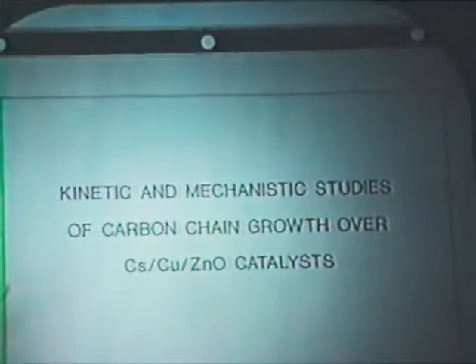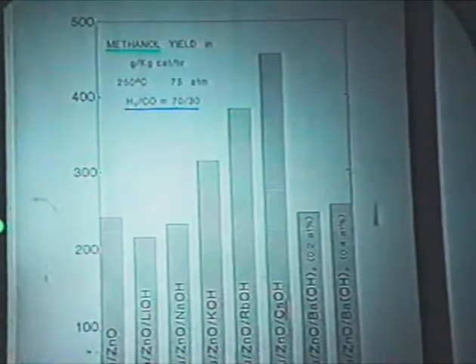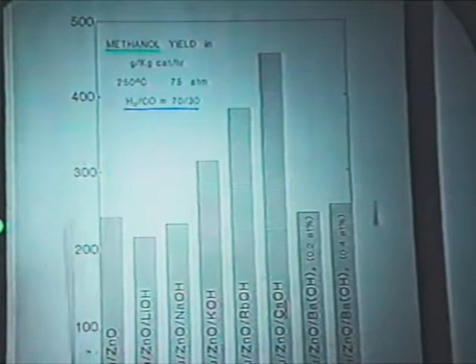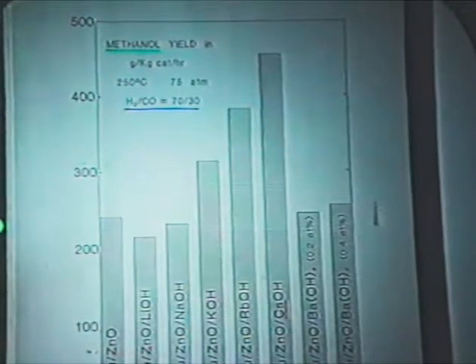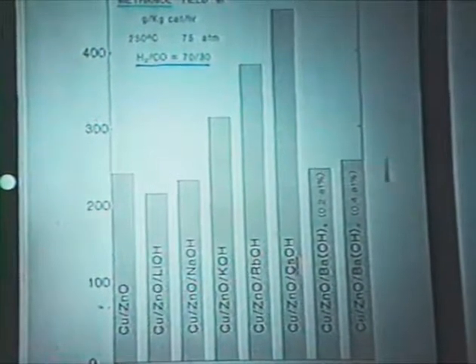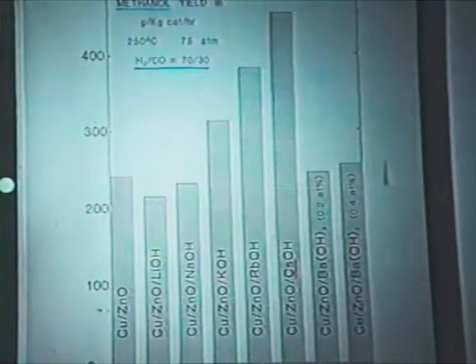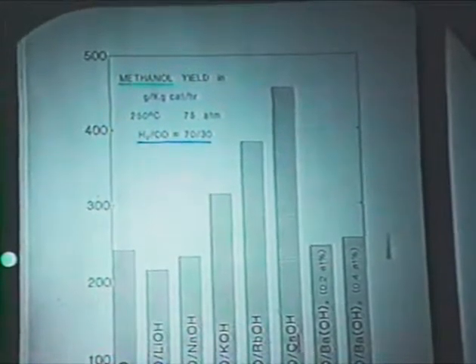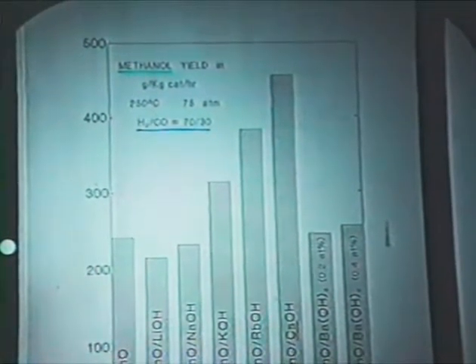Now I'd like to briefly describe our testing of copper zinc oxide catalysts and compare the proposed mechanism of that alcohol synthesis with the cesium MOS2 system. Now you might note that, again, we see cesium being a more active promoter than the other alkali. And in fact, it increases the activity with the base copper zinc oxide catalyst by approximately a factor of two. Where the doping and the alkali metals are all about 0.4 atomic percent, which is about 0.4 weight percent cesium formate or cesium hydroxide on these catalysts. This is the surface doping as carried out on the cesium MOS2 catalysts.